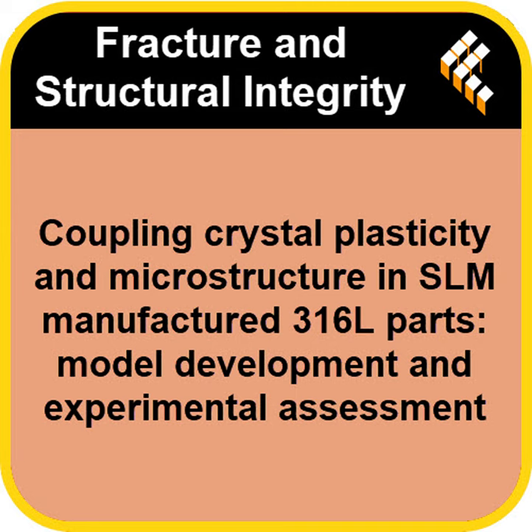That's the big takeaway. This model becomes the foundation for a digital design tool. It lets manufacturers tune their laser parameters to control the microstructure, the grain size, the twin density, before they even start printing. They can engineer the performance they need by refining the structure, not just by trying to minimize stress after the fact. That is a genuinely transformative insight.